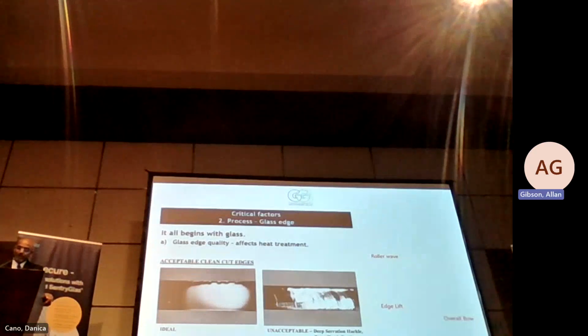Okay. The critical factor we spoke about is the interlayer. The second thing is glass, and that is the main ingredient. If you do not cut your glass properly, and that is why we are the processors, you need to be very careful of how you process the glass. If the quality of the glass edge is not perfect, it will affect your heat treatment quality.